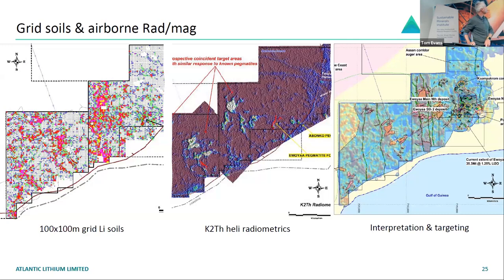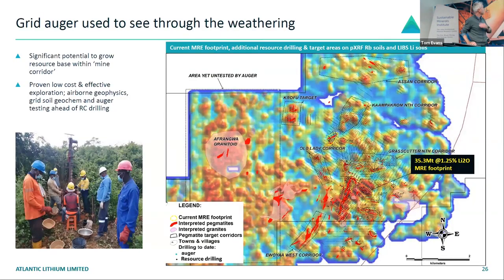So here we can see again the soils and the levels I spoke to before. The yellows are at that 1500 up to 9000 ppm. And then Ewoyaa itself, which sits here, is at that 300-400 ppm to about 600-700 ppm in soils for lithium. So using those geophysics and then mapping on the ground to highlight our target areas, and then coming in with auger, this has been a really invaluable tool for us. We've got anywhere between 2 up to 6 augers working day in, day out. It's also a good employment tool for the youth within the communities. So that really works in our favor and their favor as well. The village elders and the traditional leaders are really pleased that we're employing a lot of the youth in that regard.